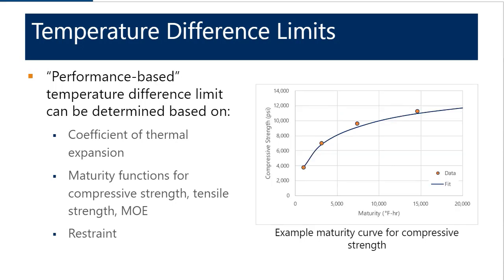Now, going back to the idea of maturity, you might be familiar with the idea of a maturity curve for compressive strength. Basically, what this does is it calculates maturity, which is essentially the temperature history of the concrete. So it's the age of the concrete times its temperature history in a very general sense. Using that maturity, you can plot as a function of maturity what the compressive strength development of the concrete is. And so you can get what's called a maturity curve for compressive strength.